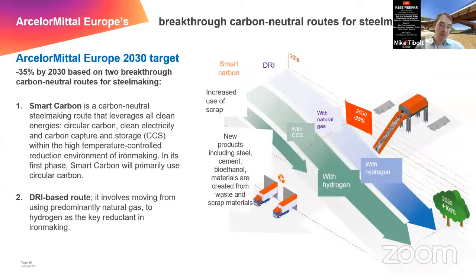And now, starting from this, how can we achieve the target, at least in 2030, to reduce the CO2 emissions by 35%? Here we have two breakthrough carbon neutral routes that we identified. The first one is what we call the Smart Carbon route, which is a carbon neutral steelmaking route that uses all clean energy: circular carbon, but also CCS, carbon capture and storage, as well as clean electricity. And this is within the high-temperature controlled reduction environment of ironmaking. As you can see in the pictures on the right, in the first phase, Smart Carbon will primarily use circular carbon and CCS technology until 2030. And then in the longer term, it is foreseen to also work with hydrogen.